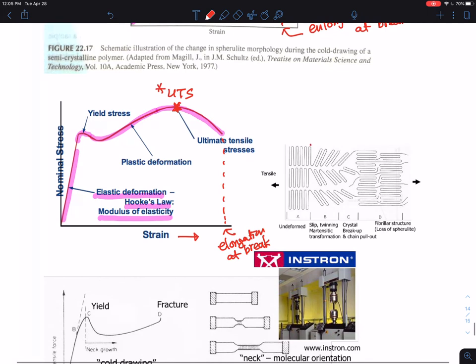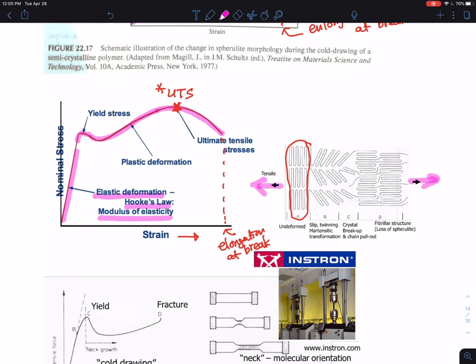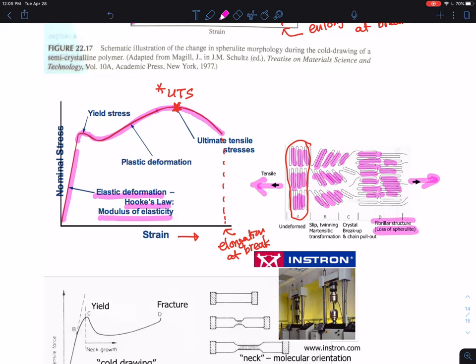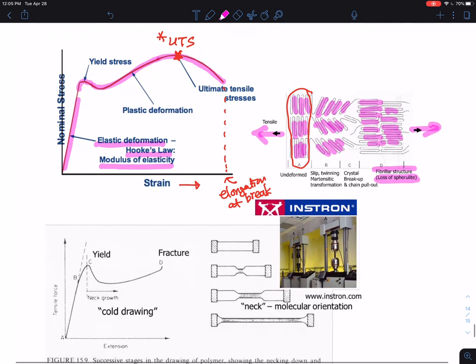The molecular picture is that before deformation you have an undeformed crystallized structure, but when undergoing tensile deformation as you stretch, the crystal chain packing starts to unravel. Eventually chains align parallel to the elongation direction. The loss of the spherulite structure is evidenced and replaced by more fibrillar structures, involving slipping and twinning — meaning two different crystal slipping directions.